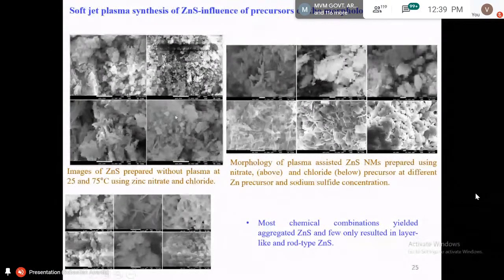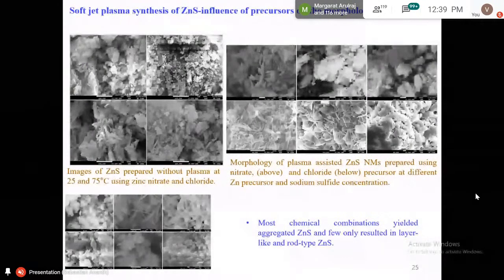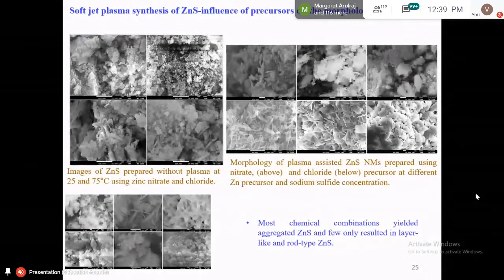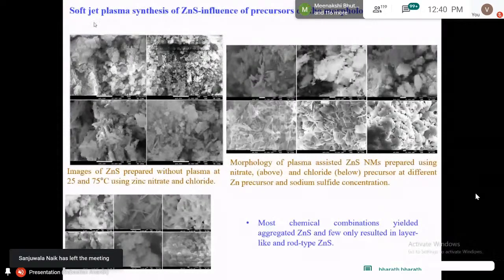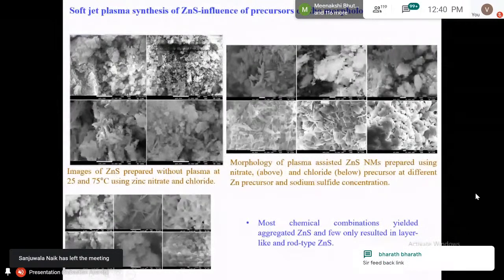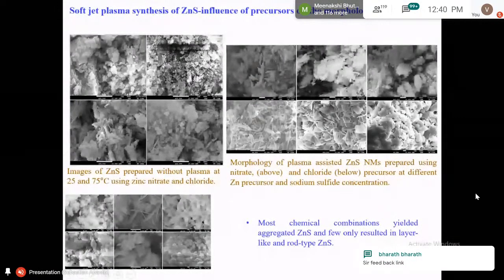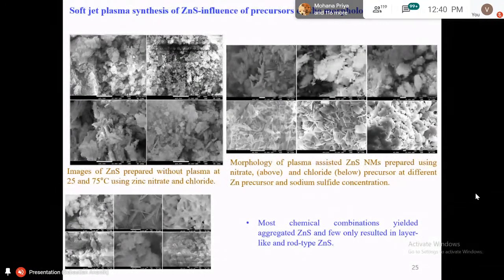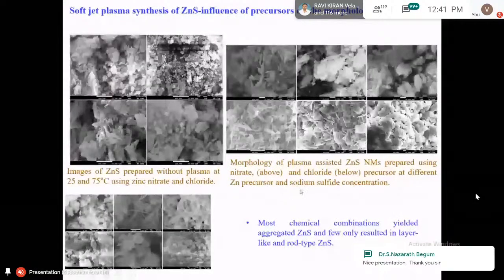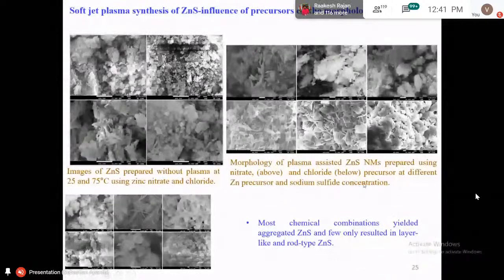If you see the literature, you can see zinc oxide has different structures ranging from one-dimensional, nanoflower, and then the layer structure. But zinc sulfide you cannot find like this. You would always find a kind of aggregated structure like this. Even now, there are not many reports on differently structured zinc sulfide. So we varied the zinc precursor concentration and the sodium sulfide concentration.